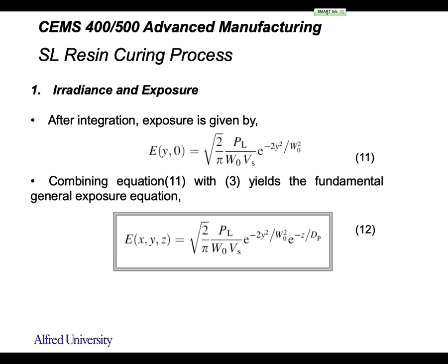Out of that many equations, it's really easy to lose focus. The E is energy, right? And what is E related to? The energy refers to how much energy of your photons is absorbed by the photopolymer, and that is directly related to how fast your photopolymerization process is. You have to make sure this energy is higher than the critical threshold, EC, for the polymerization. So it's really important to calculate this energy. You have to make sure this one is large enough.